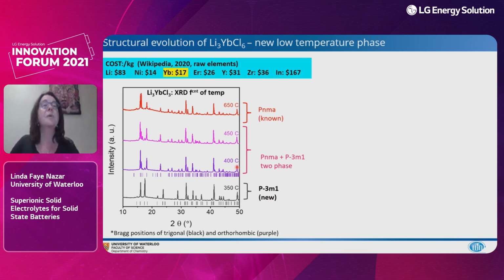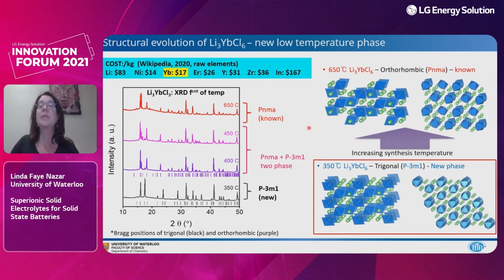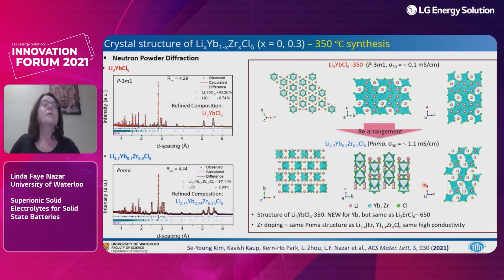And again, as we then increase the temperature, we finally form this PNMA phase, this orthorhombic phase, which is really, really similar to the one that I described for the yttrium zirconium or the erbium zirconium. So this phase has been well known, but now we have this new trigonal phase. And while its conductivity is fairly modest, this could be used as an electrode coating material because it's still good enough for that. So this is, I'll sort of zip through this.